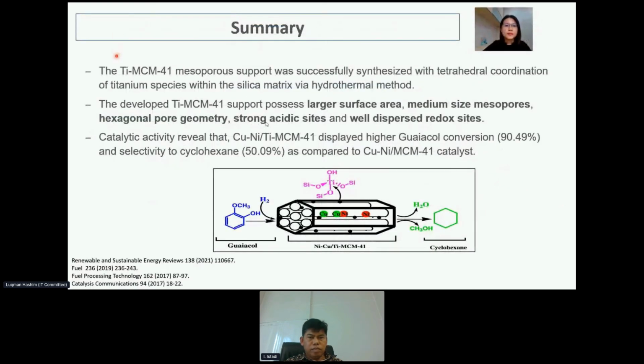As a summary, the developed titanium MCM41 mesoporous support was successfully synthesized by using the hydrothermal method, and this developed catalyst shows the largest surface area, medium-size mesopores, hexagonal pore geometry, strong acidic sites, and well-dispersed redox sites, which make it a potential catalyst for this deoxygenation process. For the catalytic activity study, it indicates that this developed catalyst shows a higher guaiacol conversion, around 90%, with a high product selectivity of 50% as compared to the unmodified catalyst.